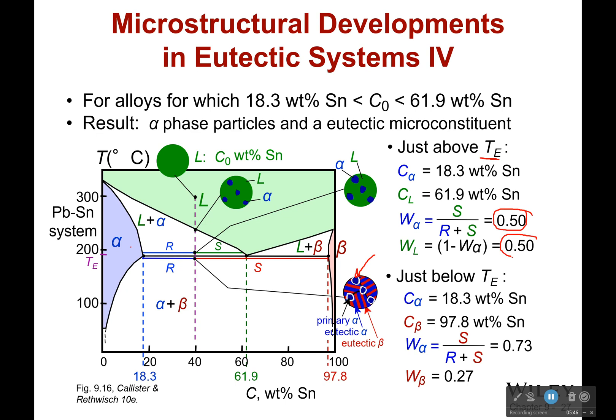So just above it, 50% for both of those. And then just below that, weight fraction of alpha has changed to 73%. So that's why we see these grains in here, these pure alpha grains inside of it. And then we have this 27 weight percent beta phase, which is actually in the lamellar structure.